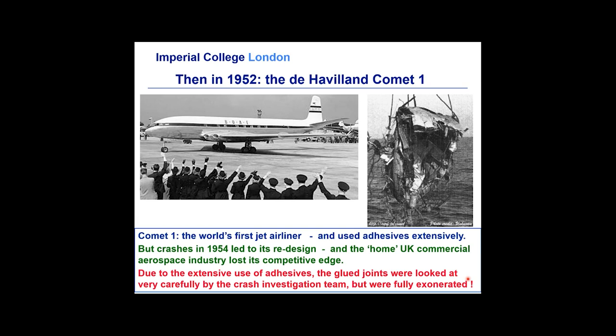However, fatigue cracking of the aluminium alloy from the corner of the navigator square window, seems odd these days, doesn't it, having a navigator with a sextant, but that's the way they crossed the Atlantic, led to the complete failure of several aircraft, and all the Comet 1 aircraft were grounded and redesigned over the next few years, but still are using adhesive bonding. Indeed, due to the very extensive use of adhesives, the glue joints were looked at in great detail by the crash investigation team, but were fully exonerated. And today's adhesives are used extensively in aerospace and automotive industries.